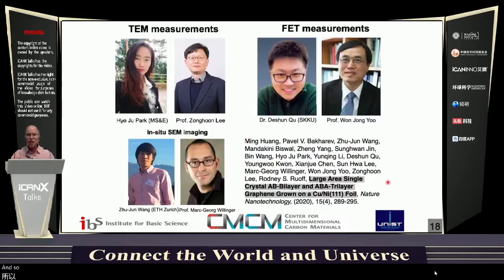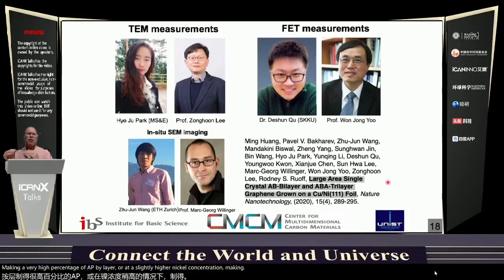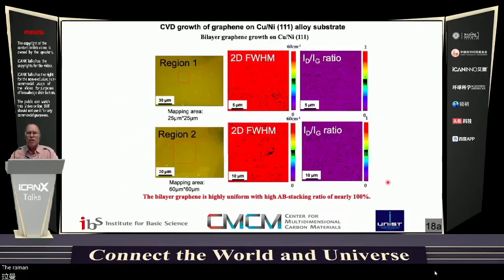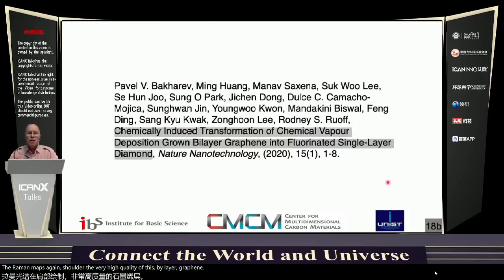And so colleagues shown here were very helpful, and all co-authors in the paper we published on making a very high percentage of AB bilayer, or at a slightly higher nickel concentration, making maybe about 60% of the area covered with trilayer, which turned out to be ABA stacked. The Raman maps again show the very high quality of this bilayer graphene. So let me now come to this topic of single layer diamond, fluorinated single layer diamond, also referred to as F-diamane.